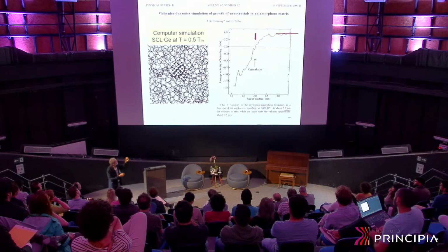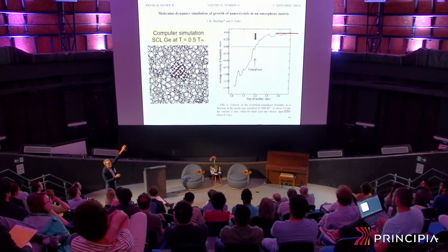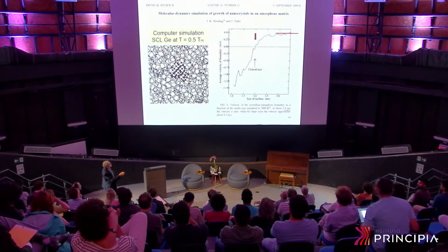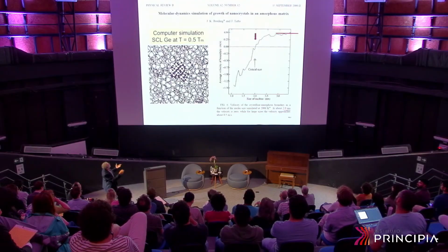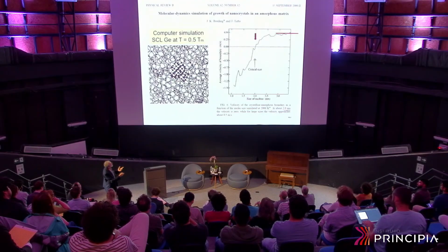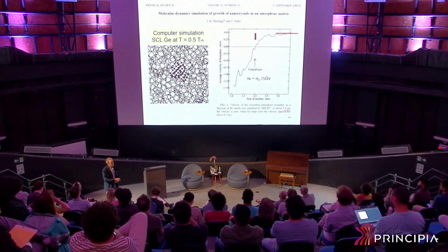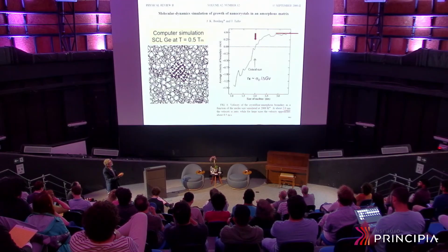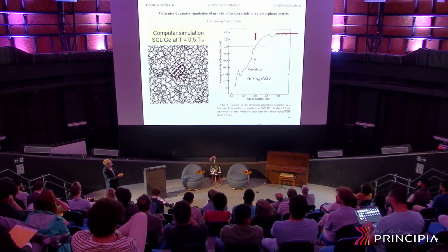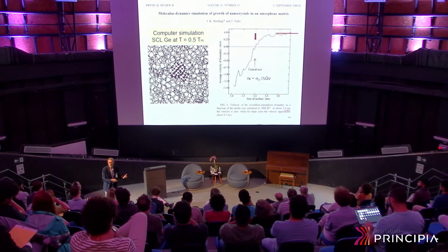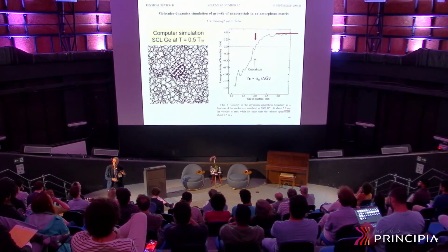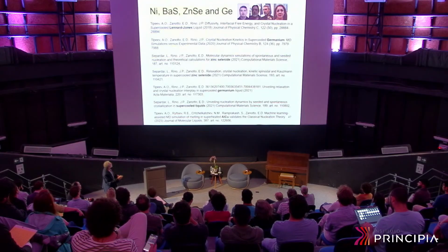So by playing games with the size of this artificial cluster, we can get the critical size at different temperatures. If we can get the critical size, we can calculate the interfacial energy because delta G is known for most of this system. So by MD, you measure actually the critical size and then measure delta G and calculate the interfacial energy. So now we have a way to avoid the assumption about the interfacial energy,